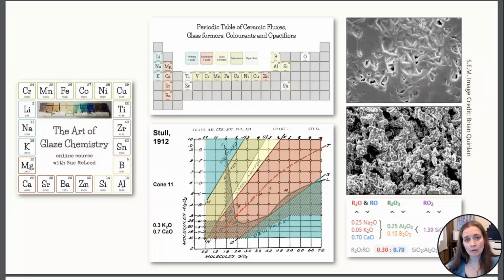And then during the cooling cycle, crystals grow within the liquid and in the glass, and that's what turns the glaze into a matte glaze. This image here is an underfired matte glaze, where it's just a bunch of particles that are fused together, and they're very vulnerable to break down. Like they haven't formed this really strong, durable surface yet.